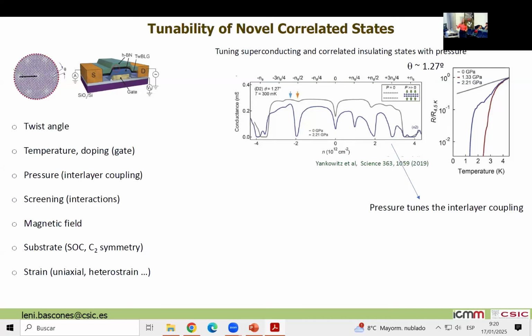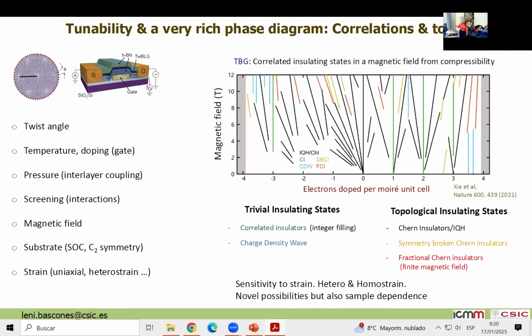But what was found is that by applying pressure from above, they can really tune the superconductivity. See here, you see these minima, which are really associated with the insulating states that were tuned. But here you can also see.